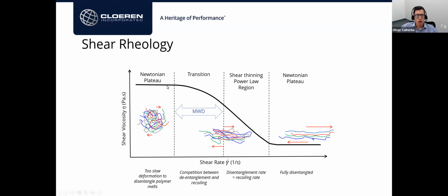You can see the viscosity is initially Newtonian at low shear rates, then starts to shear thin. Eventually, we are shearing the material so fast that everything is disentangled, and we reach another theoretical plateau at low viscosity and high shear rate. For polymer melts, though, we rarely see that plateau because we are in a shear rate region covering the Newtonian plateau, the transition region, and the shear thinning region.